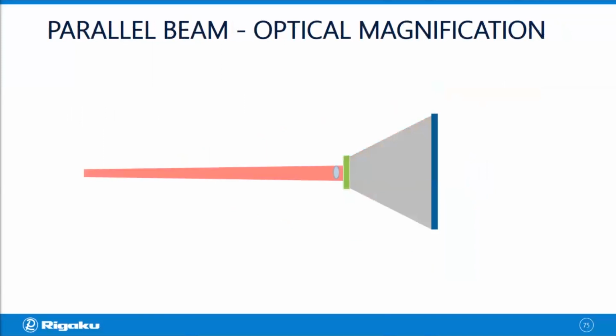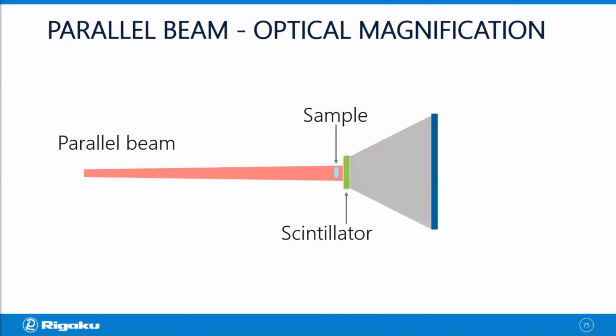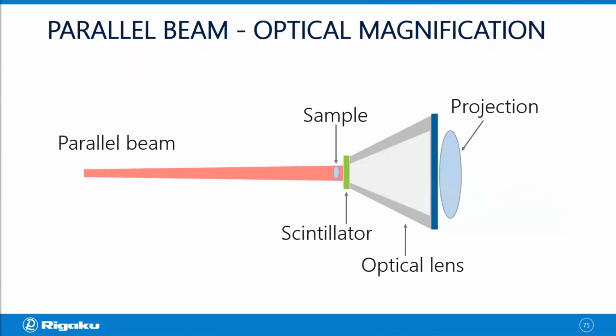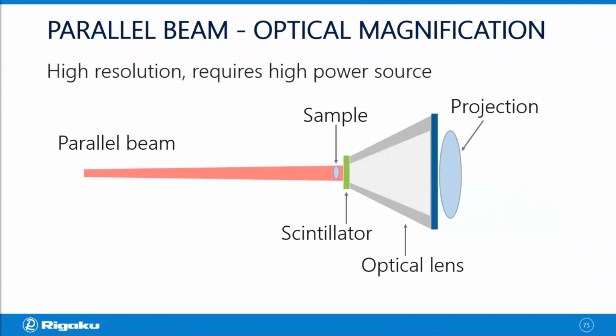For the parallel beam geometry, we use the optical magnification. So you have a parallel beam, now you don't have a lot of divergence. Then you put the sample right up against a scintillator, which converts X-rays into visible light so that you can use optical lens to do the magnification. And this geometry actually works very well for high resolution imaging. But at the same time, it requires high power X-ray source. And that's because we are using only parallel portion of the X-rays. And also you have to use pretty thin scintillator to achieve a high resolution.